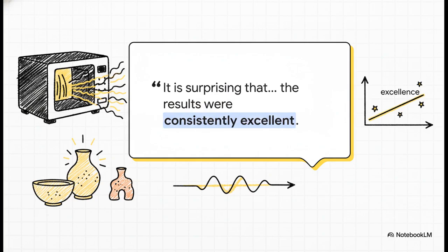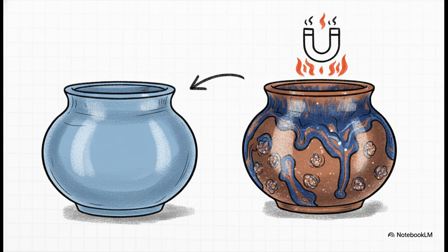Even the lead author of the paper, Bruno Goffet, was surprised. He actually wrote, "It is surprising that despite a lack of precise temperature and power control, the results were consistently excellent. That tells you this method is surprisingly forgiving." And let's not forget about that extra creative control. Using those magnetite-heavy susceptors gave artists the power to create those gorgeous, complex glaze effects that come from a low oxygen firing. That is a huge, huge benefit for a kiln that runs on electricity.